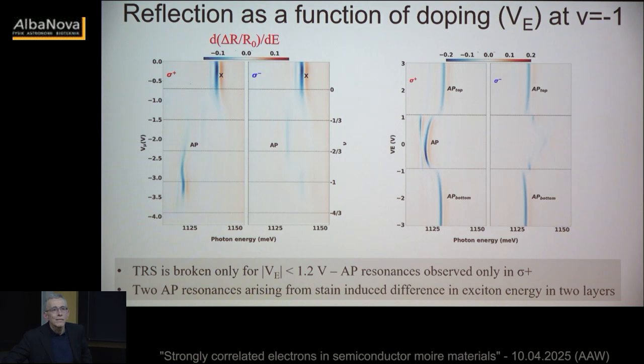Okay, another question is how do you know it's a trion and not like a bi-exciton? So in this case it's easy because it's a trion, because we have very low density of excitons, and the strength of this attractive polaron resonance, or in photoluminescence trion, increases linearly with the exciton density, whereas bi-exciton should increase quite rapidly. And we see bi-excitons of interlayer excitons and intralayer excitons, so bound state of excitons. But that's a different animal that I have.